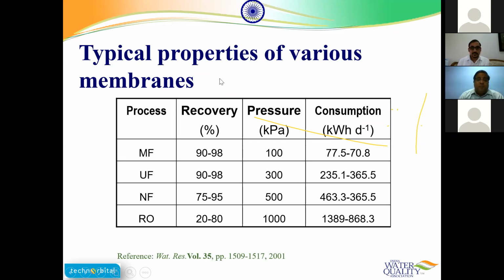NF, compared to MF and UF, has very small porosity sizes, so the pressure requirement is higher compared to MF and UF. Then again we go to RO, where the porosities are extremely low and we need very high pressure. You can see for, say, 100 KLD water treatment, the energy consumed by MF and RO has a huge, like 20 times, difference. And it is rightly so, because we need very high pressures in RO.